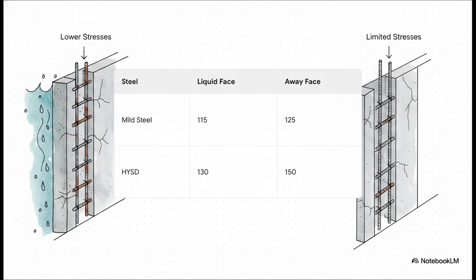On the liquid retaining face, mild steel is strictly limited to 115 newtons per square millimeter, and HYSD bars are capped at 130. And even on the dry face, away from the liquid, HYSD is still maxed out at 150. Basically, we are deliberately understressing the steel so the surrounding concrete doesn't stretch and crack.